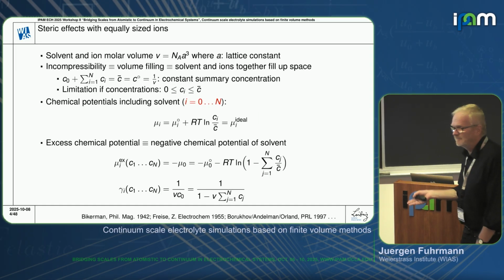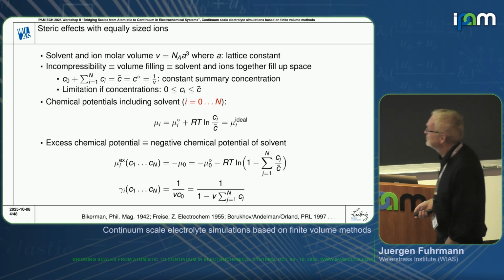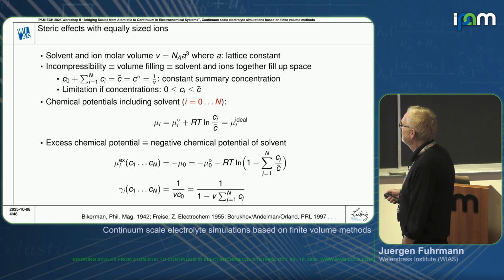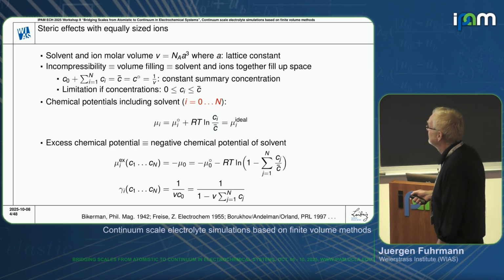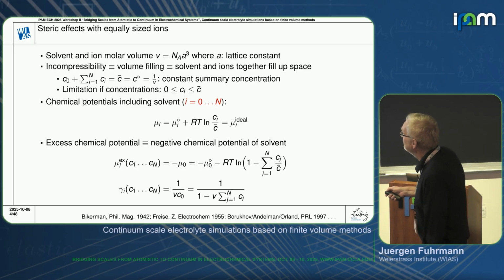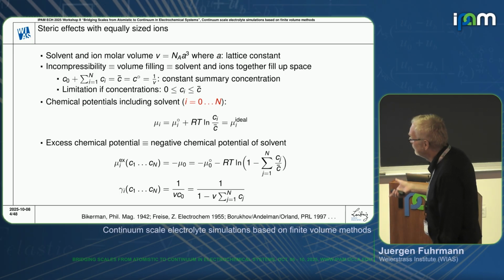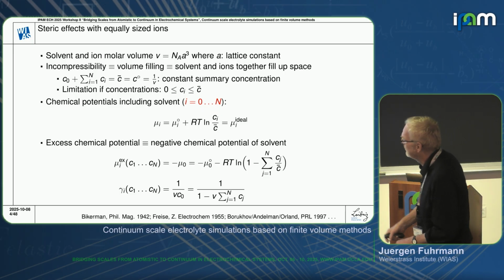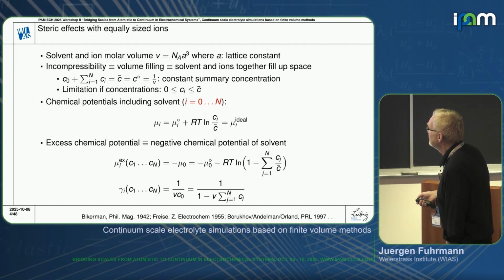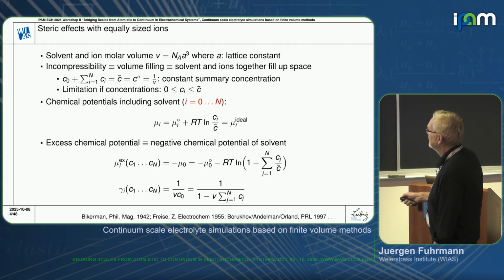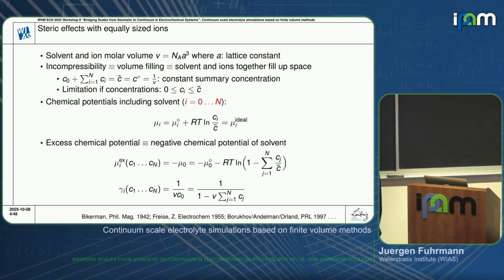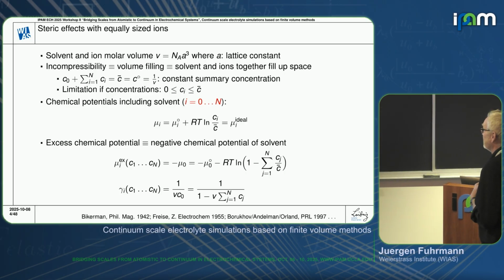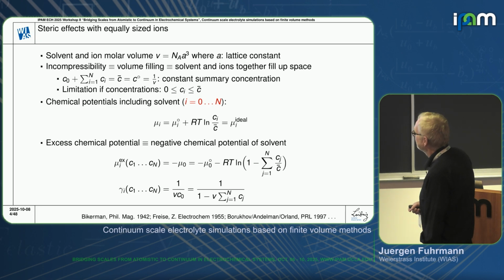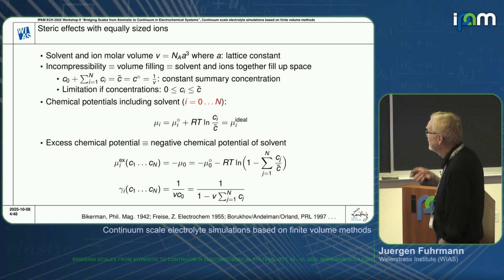I didn't say anything about the excess chemical potential yet. The simplest way to introduce steric interaction would be to assume that we have a lattice with a lattice constant A, which gives rise to a fixed molar volume, which is the same for the solvent and for all other charged species. We assume that the summed concentration fills up space, which immediately gives us a limitation of the concentrations, so that we don't exceed some maximum concentration, which is one of the important features of these models if you look already at equilibrium problems.